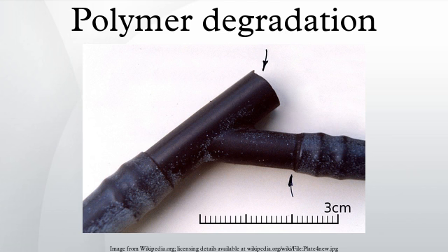Polyamide is sensitive to degradation by acids, and polyamide moldings will crack when attacked by strong acids. For example, the fracture surface of a fuel connector showed the progressive growth of the crack from acid attack to the final cusp of polymer. The problem is known as stress corrosion cracking, and in this case was caused by hydrolysis of the polymer. It was the reverse reaction of the synthesis of the polymer.